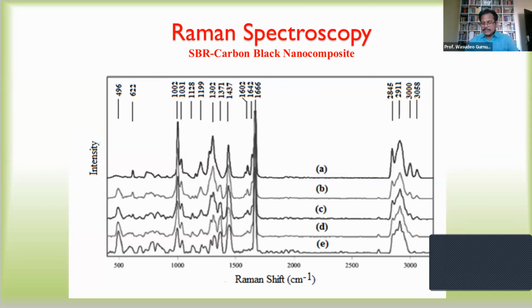We are here in the case of Raman spectroscopy. This is the spectra shown for SBR and carbon black composite, and here the rubber, which contains asymmetric methylene or methyl stretching vibration, can be known around the 2800 to 3000 inverse centimeter region. Carbon-carbon double bond stretching vibration of the rubber can also be obtained at around 1666 inverse centimeter, and the intensity of Raman peaks depends on the blend composition. So different peaks and characteristic signals are known from this Raman spectroscopy. So it is one of the powerful tools to characterize our rubber.